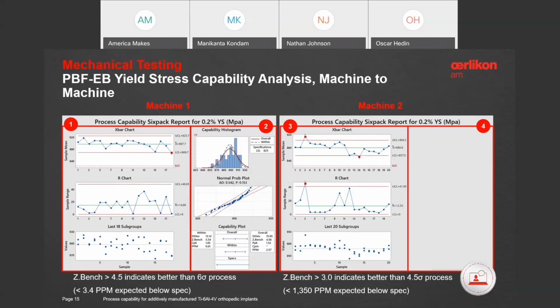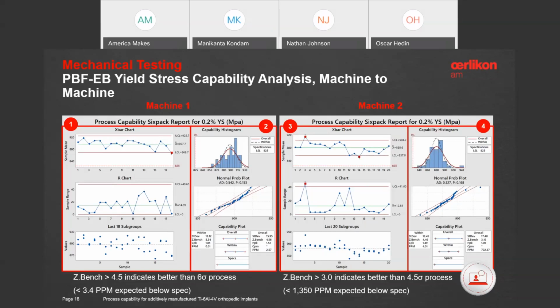If we turn our attention to the second machine, we will see a similar pattern emerge. From the 20 builds that were printed, a total of 40 coupons were tested with no test failures reported. The process averages largely remain within limits, and there are no signs of center shifts or linear trends. However, the process spread for machine number 2 is a little bit higher, and we also have a few outliers. As a result, the Z-score for machine number 2 hovers around 3, indicating that the process performs at a sigma level of approximately 4.5.